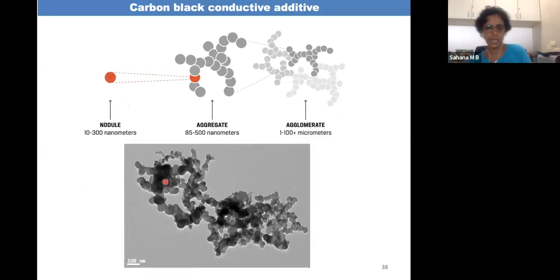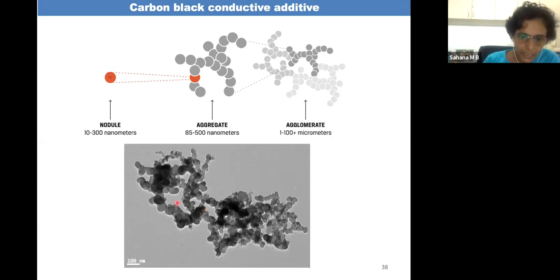Now, this is the carbon black, which is one of the main ingredients of the slurry of the cathode and the anode material. The viscosity or the rheology of the slurry can be very easily tailored or tuned with the help of the carbon black. How the carbon black is distributed in the structure determines the rheology in many cases, other than the binder.